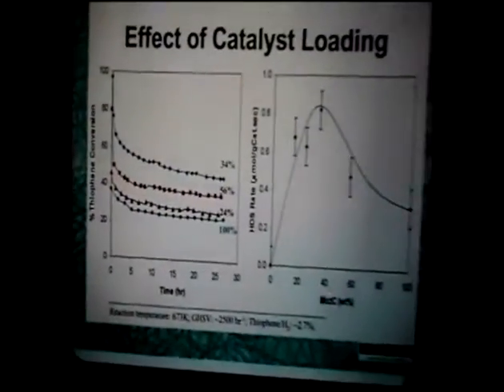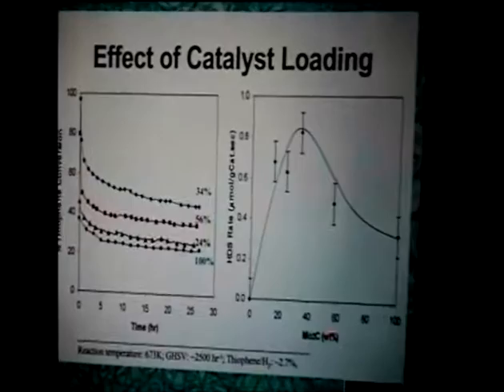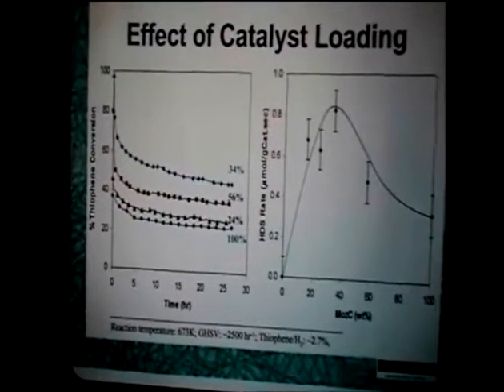So that's much better to start with carbide, even if you have a problem with surface area. And here is a plot with catalyst loading. What happens when you change the loading? Here is the 100% molybdenum carbide, and this is the loading on the molybdenum carbide in the fibril. And here is the time versus conversion plot, and maybe easier to look, here's all the catalyst molybdenum carbide and the rate per gram of catalyst.